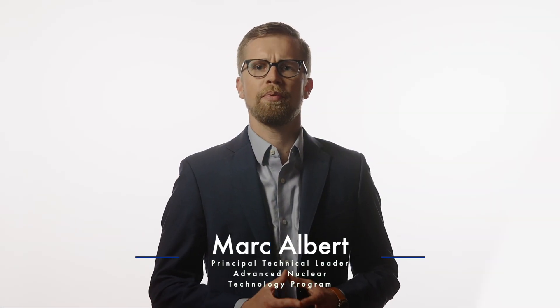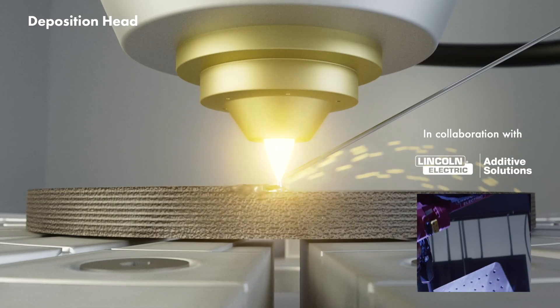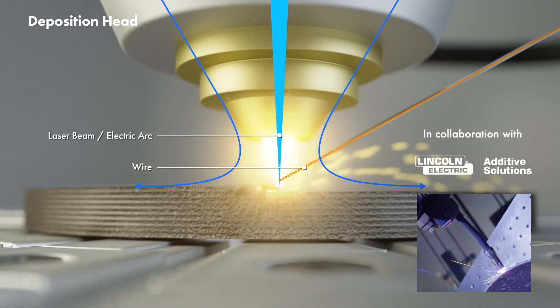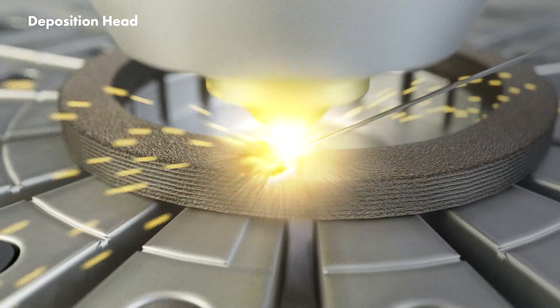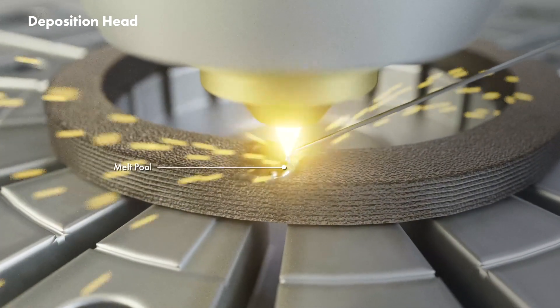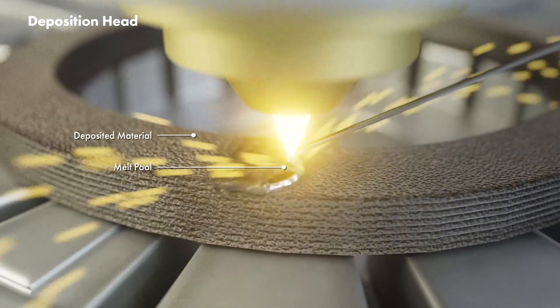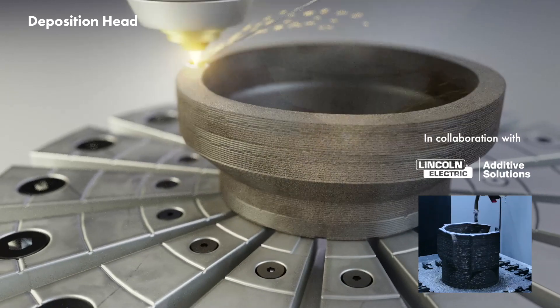Advanced manufacturing is something that EPRI has identified as a vital part of deploying new nuclear at scale around the world. Directed energy deposition, or DED, is one such technique. DED starts with a deposition head — a nozzle that feeds a wire heated by an electric arc and protected by shielding gas. The arc creates a melt pool on the base material, which joins the melting wire to form a layer of deposited material. This robotic head then works in layers similar to 3D extrusion printers until it builds up to the component.